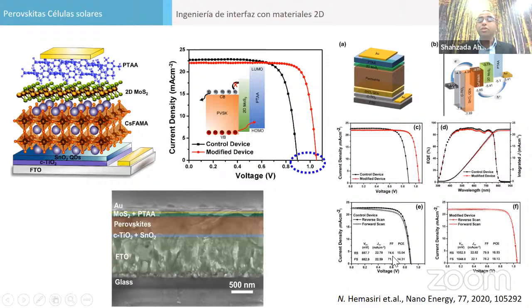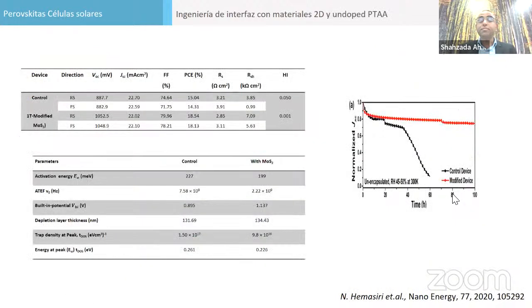So without MoS2, the devices give 15%, and with MoS2, we can go to 18% efficiency. We characterized some electrical parameters to understand why it happens. We found the built-in potential was higher, the defect density was lower, and the trap density was lower, and that's why the device improved. But the good thing is that you can see the stability of the device was much higher than that one.